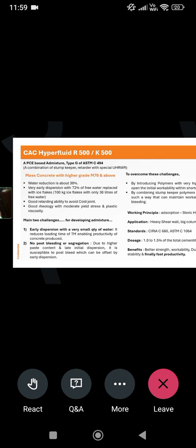And what is the disadvantage? What problem will happen if we go with this combination? Your dispersion time will be higher. Your TM loading time will be higher. Your productivity will be low. You may have late dispersion because initially it will not be dispersed. These are the kinds of challenges you may face when a high amount of ice and a low amount of water is used. So we need early dispersion with very small quantities of water, reducing loading time. I already told you about no post bleeding and segregation, as it is not mixing very fast. During transport, it gets split.